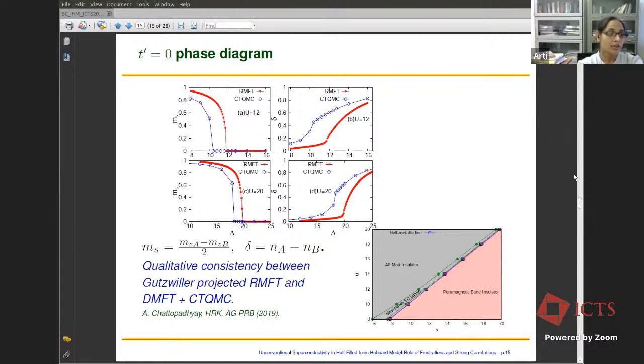So you can see that there is a qualitative consistency between the two methods. The Gutzwiller projected renormalized mean field theory actually captures the correct trend of various physical quantities like the staggered magnetization on the two sublattices and the difference in density on the two sublattices, although it cannot provide the correct transition point. The transition point obtained from RMFT is of course larger compared to the one from DMFT plus CTQMC calculations because of the missing quantum fluctuations in the RMFT calculation.